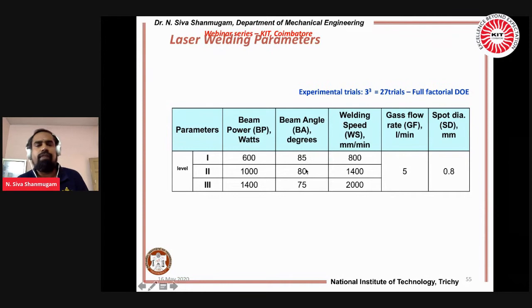Beam angle is 85, 80, 75. And the gas flow rate, for removing the plasma plume as well as the protection of the weld puddle from the atmospheric contaminations, I am using a gas flow rate of 5 liters per minute. This is delivered with the help of the copper tubes, and the spot diameter which I maintain is something about 0.8. So 0.8 means it is something around 160 mm focal length.